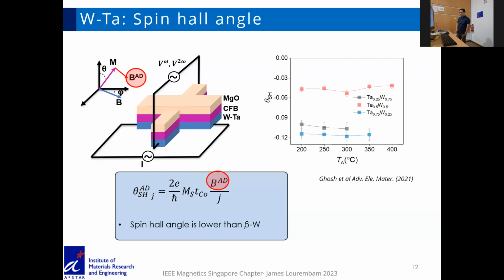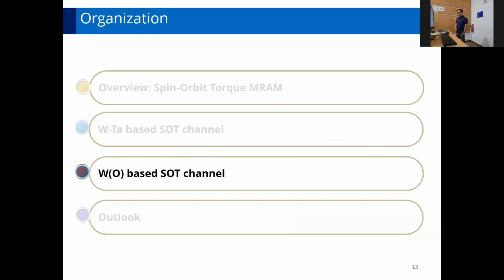What we found is, well, our original quest was to get a value higher than beta phase tungsten, which is about -0.3. We find that while doping or making tantalum multilayers modulates the spin Hall angle, it does not make it better than what has been reported so far. So with this, we looked into a different system, which is an oxygen doping system in tungsten, to see if we can make it better than the tantalum-tungsten multilayer, because the spin Hall angle was not as high as we wanted.